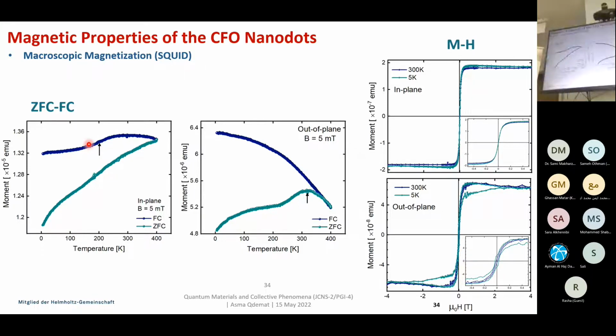So what we can see is the difference between in plane and out of plane. In plane, we can see that at this point we have the maximum of the zero field cooling, from which we can obtain the blocking temperature, the temperature between the blocking state and the superparamagnetic state. And we see some decrease in the field cooling, which is an indication of the magnetic interaction between the nanodots.